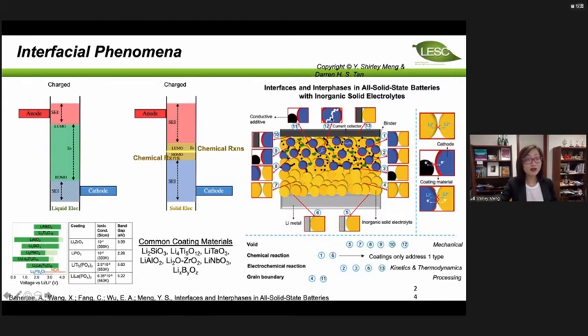Now, in the solid, if during the synthesis you have a void, an empty space, that's not good because you have created a lot of extra interface. So in this chemical review paper, we said you have at least six extra interfaces compared to the liquid electrochemical cells, because the void can also play a very important role. And for this reason, in solid state batteries, mechanical compatibility or mechanical properties become such important topics beyond just the electrochemical interface, right? So for interface stabilization, I can apply many tricks like coating materials. With 10 years of experience in cathode coating, I think we are quite comfortable doing the coating. But this mechanical strength is something that really, really surprised me.